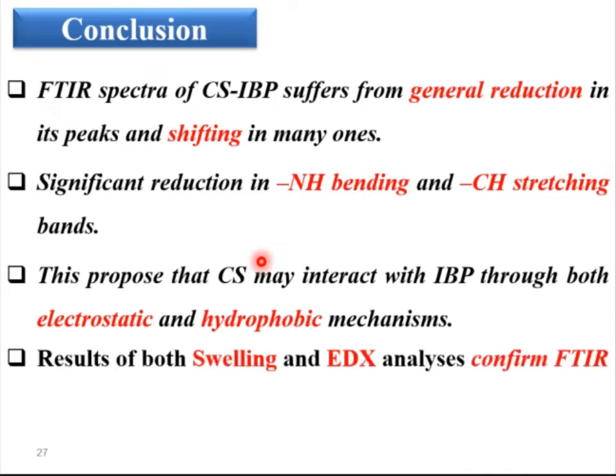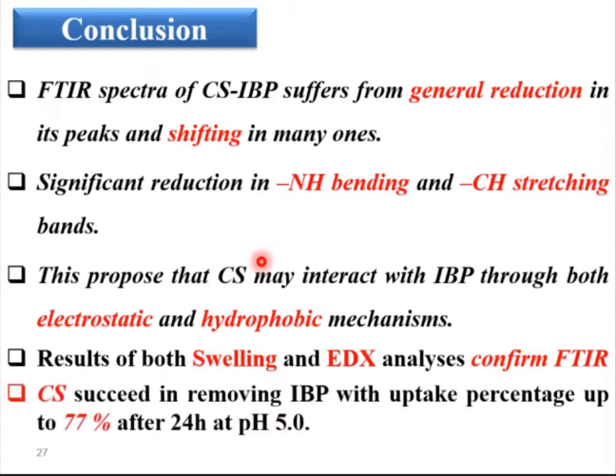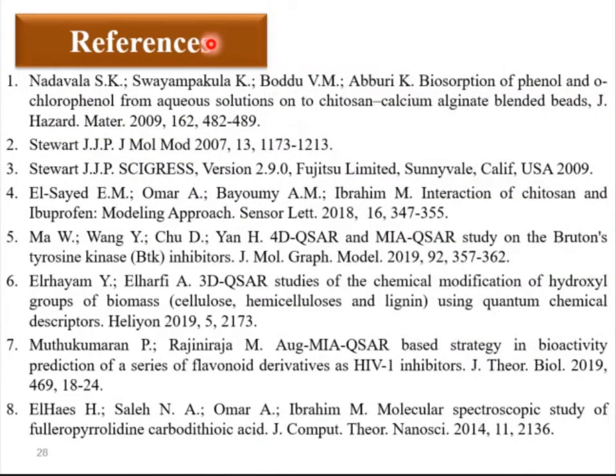Results of swelling and EDX analysis confirm the IR spectra, and chitosan silica succeeded in removing ibuprofen with an uptake percentage of up to 77% after 24 hours. Then these are our references, and thank you.